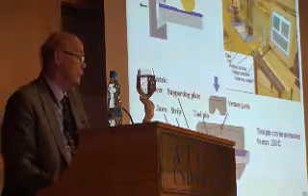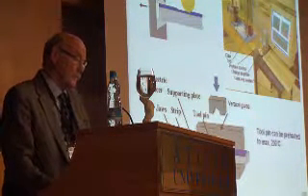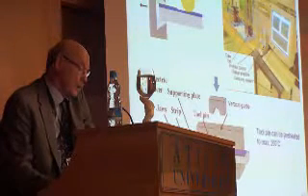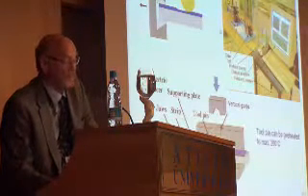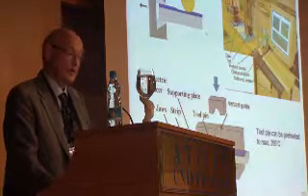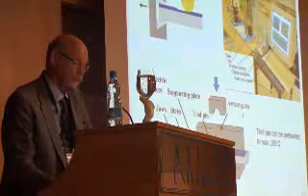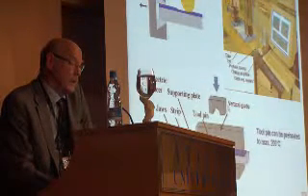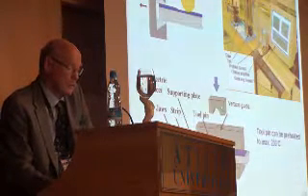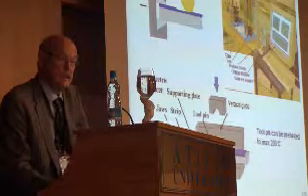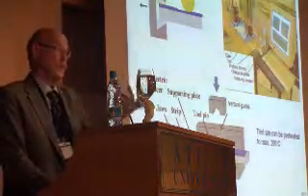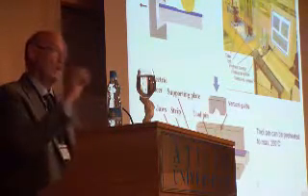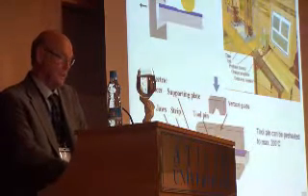The third test is a strip reduction test, where we load the strip with a tool pin, a non-rotating tool, and then we draw it with a hydraulic cylinder to deform the strip in a strip reduction, similar to an ironing operation. This is a dedicated machine for this purpose. The tool pins here can be heated to maximum 200 degrees C by electric heater cartridges inserted in this loading tool. They have a square end surface in order not to rotate, and we can turn the tool 4 times, testing with the same tool surface, say 4 different lubricants, or repeat the test, and then know that we have exactly the same surface properties in the 4 tests.